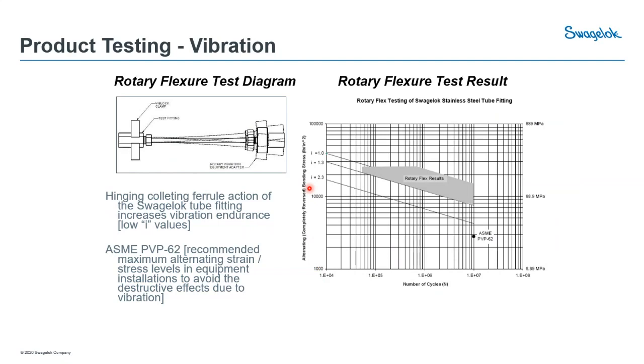Now, the gold standard for fittings when you look at vibration resistance, that's a butt weld. So you can see here this line is an intensification factor of 1.0. That's a butt weld. When we go to a high quality socket weld, it's about 1.3, so a little bit less than that butt weld. If we look at threaded connections or NPT, it's actually below this third line in this lower region, so it's below 2.3 for the stress intensification factor.